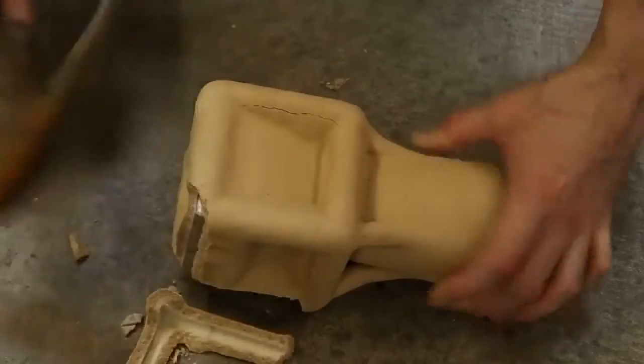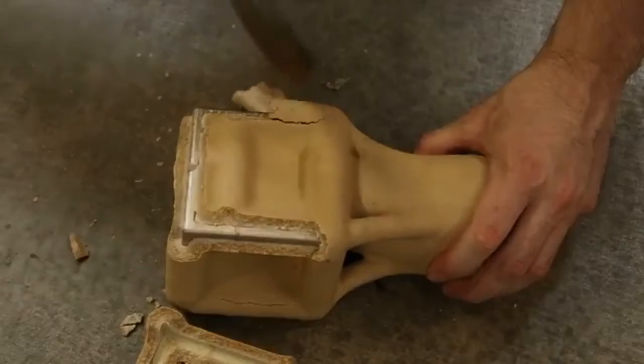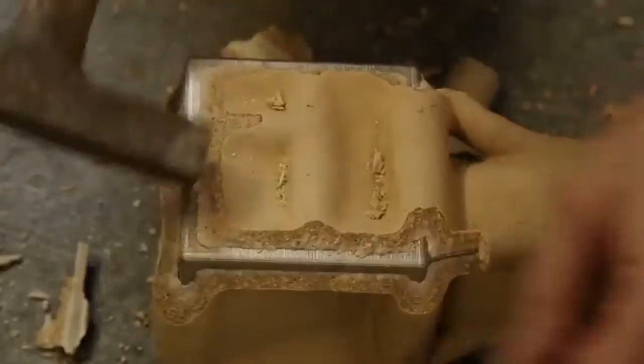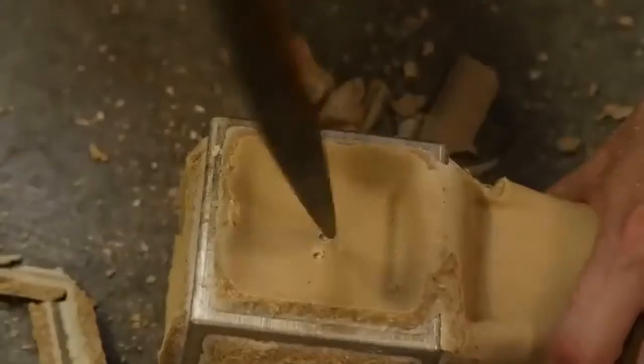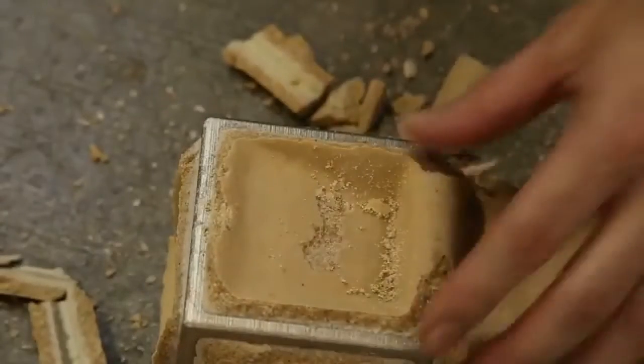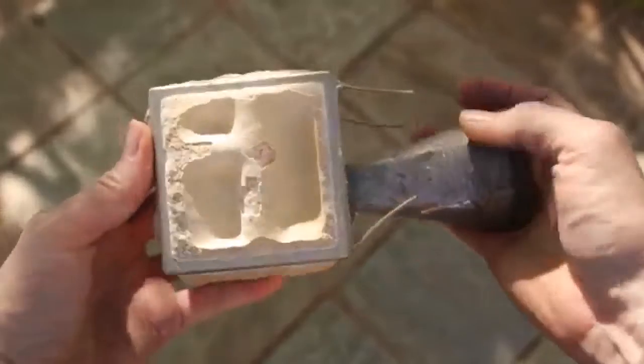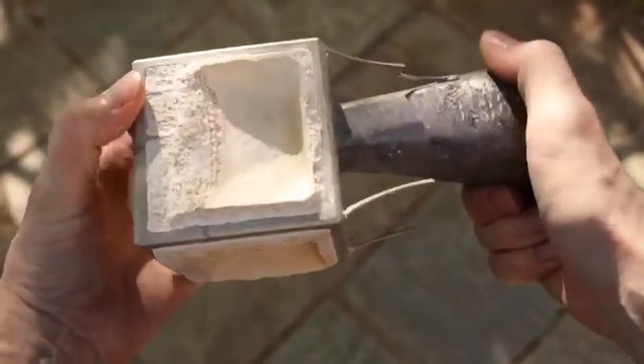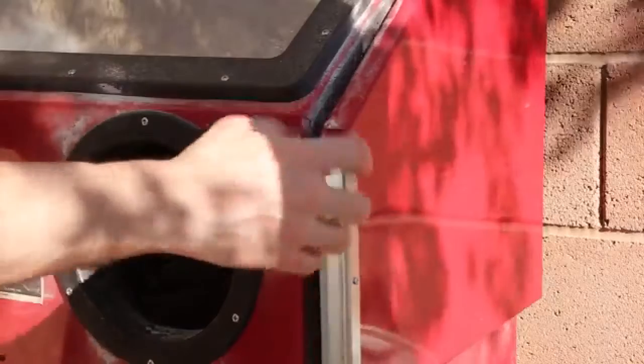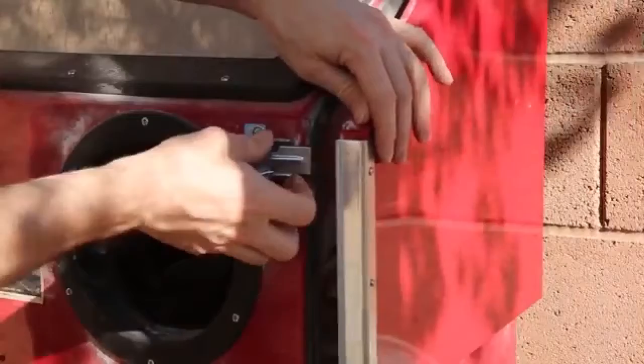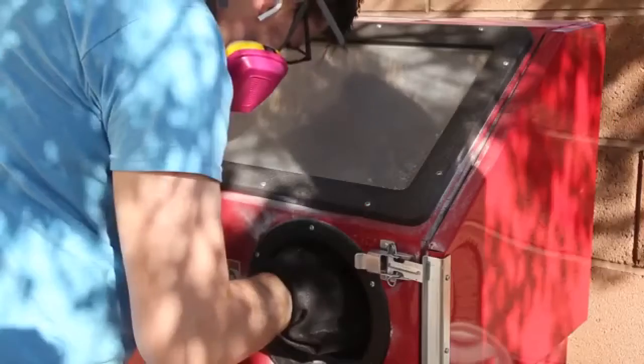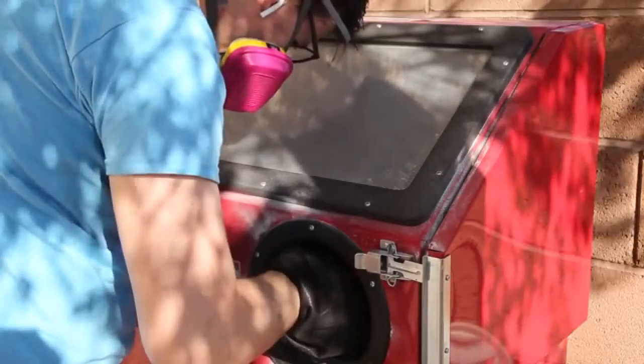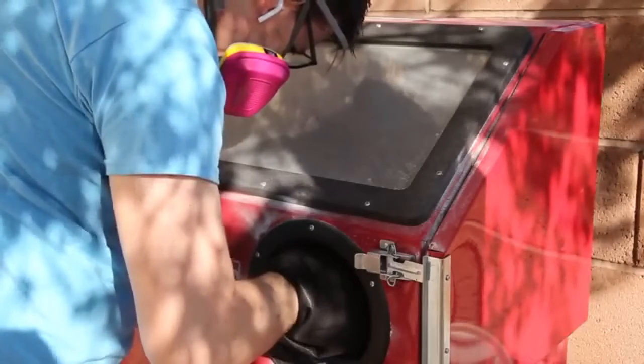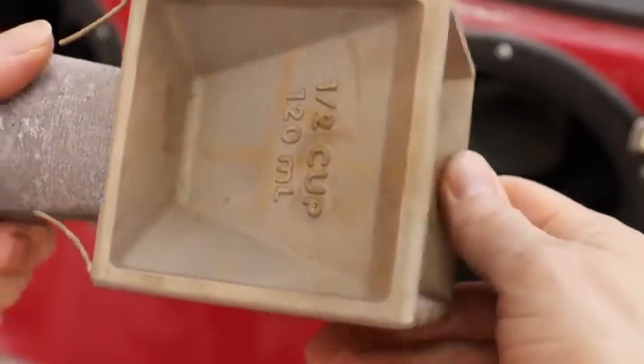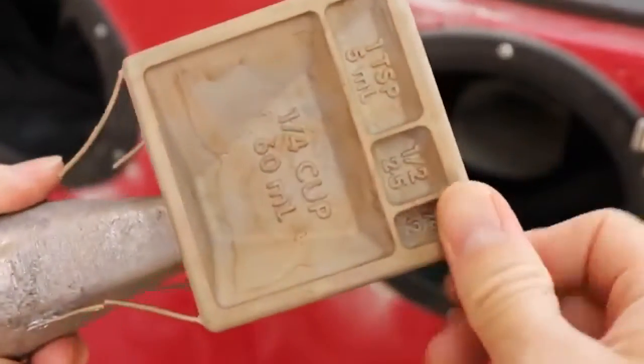Then I started to chip off the shell with a hammer, but because of the shape of the casting, I hardly got any of it off. Removing these shells can be really difficult, especially if there are a lot of indentations on castings like this one. Fortunately, I have a sandblaster, which made the job a lot easier, but it still took about 2 hours to remove all of it. After removing the shell, I was happy to see that the mold filled out properly and the casting looked good.